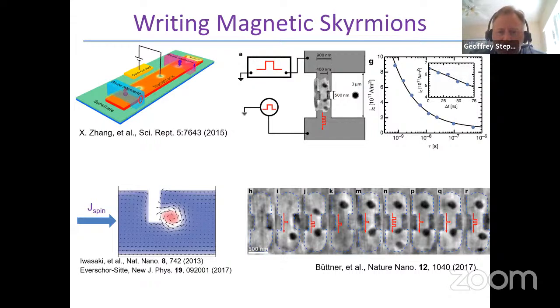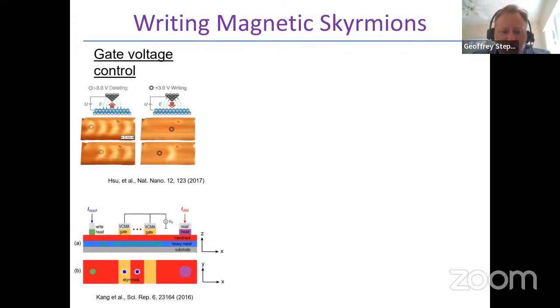But the current densities that are required, both to translate, but certainly to nucleate magnetic skyrmions, are quite high, and certainly much higher right now than would be allowable for a real device application. So another way to do this is by using electric fields. And there have been a number of proposals, some experimental demonstrations, of using a gate voltage to control, for example, the magnetic anisotropy localized in a region of a film that could allow the creation of a magnetic texture like a magnetic skyrmion.